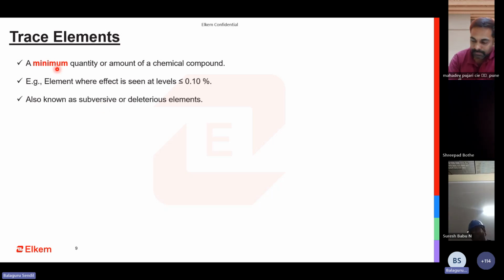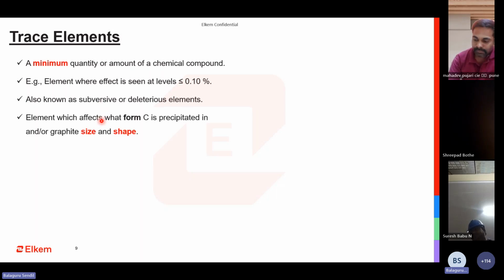It is the minimum quantity that is allowed, and anything above that can actually influence the form. So, an element which affects what form carbon is precipitated in. The form here is that it can either come out as graphite, or it can be promoted as a carbide. Most of the time trace elements tend to promote it as a carbide, and even if it is promoted as a graphite, during the later cooling period it can also influence the shape and size.